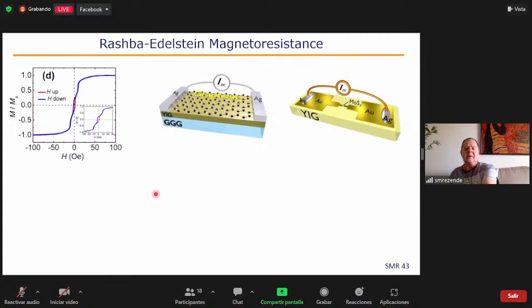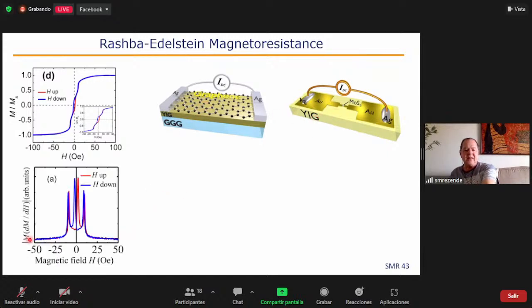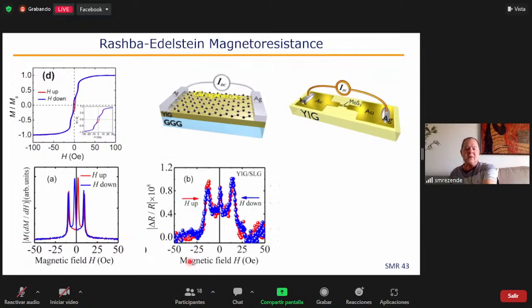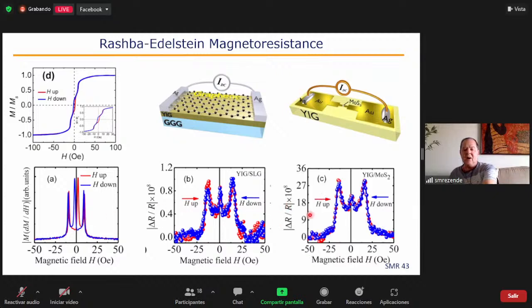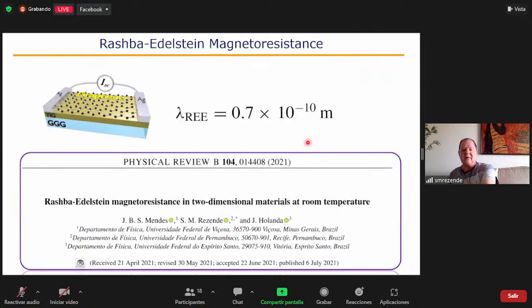And we did this experiment, as I said, with graphene on YIG. And here is the result. We vary the magnetic field. So this is the change in the magnetization. This is the change in resistance. The change in resistance reflects the change in magnetization of the YIG film, and also of the two-dimensional semiconductor. So this is the Rashba-Edelstein magnetoresistance. That was observed very recently, and this paper was published last year.